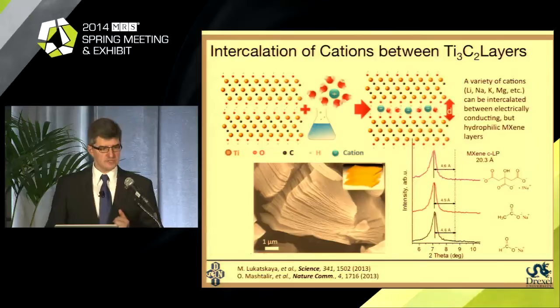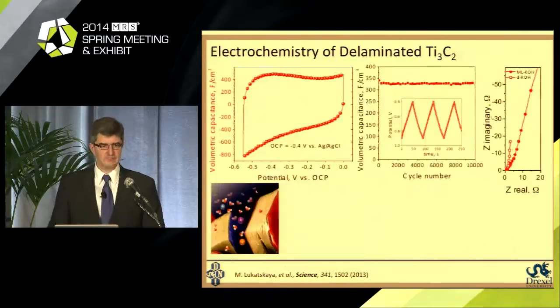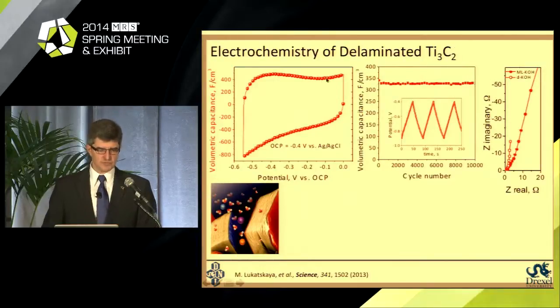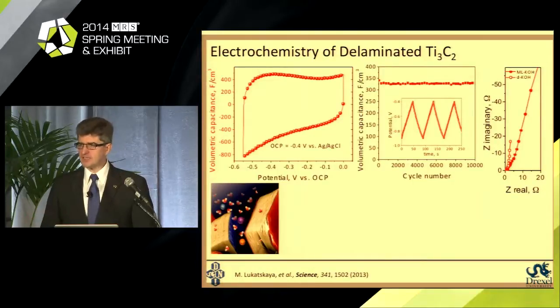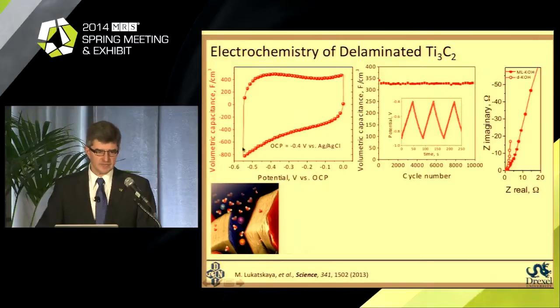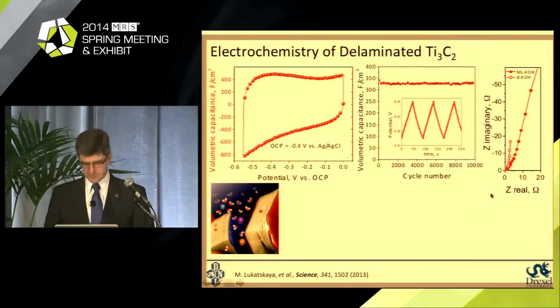And what is also important, of course, you can intercalate ions between these layers just like you intercalate ions between graphene. But when we did capacitance measurements on those materials, we found that, unlike in graphite, they show real electrochemical behavior, with intercalation of lithium ions, for example. We get pretty rectangular cyclic voltammograms. We get ideal, virtually triangular galvanostatic charge-discharge curves. And we get extremely stable capacitance for 10,000 cycles, with very low resistance, as this Nyquist plot shows.